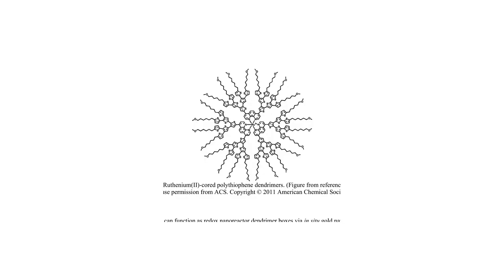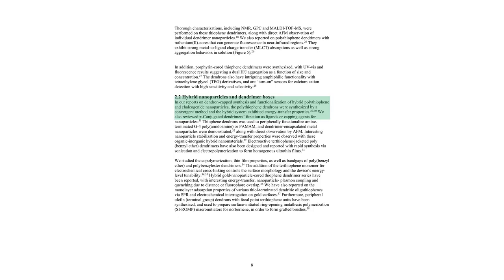Another variation involved a porphyrin core, which led to interesting aggregation behaviors that were dependent on the dendrimer's size and concentration. Building on this, the authors explored the creation of hybrid nanomaterials. They used polythiophene dendrons as capping agents to synthesize and stabilize nanoparticles, such as cadmium selenide quantum dots. In these hybrid systems, the organic dendron shell can interact with the inorganic nanoparticle core, leading to useful properties like